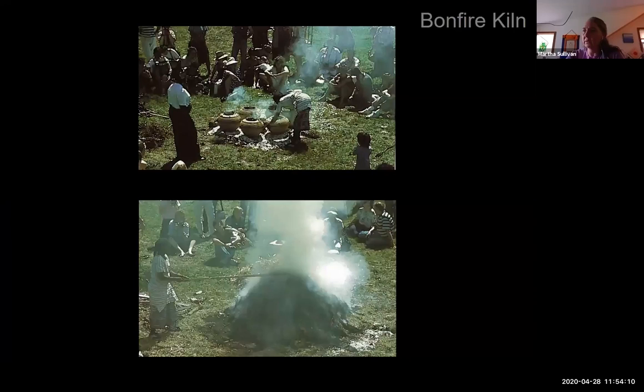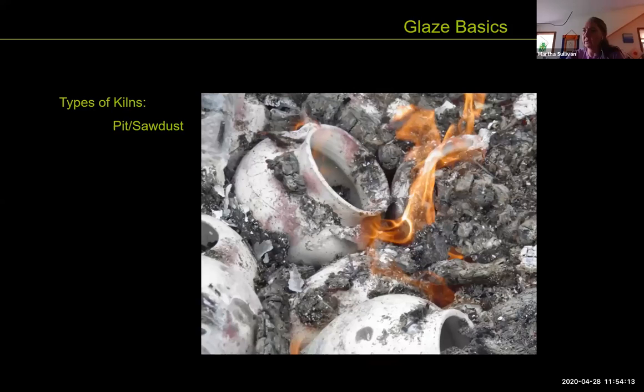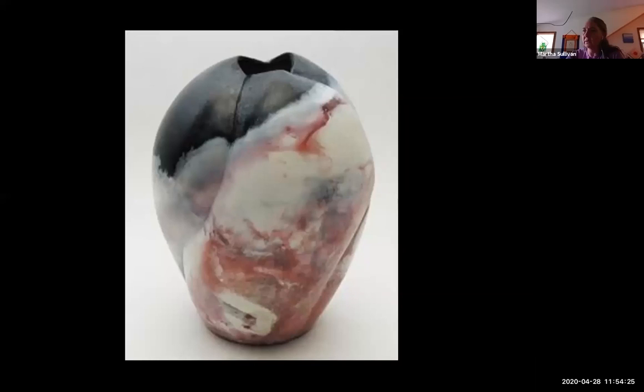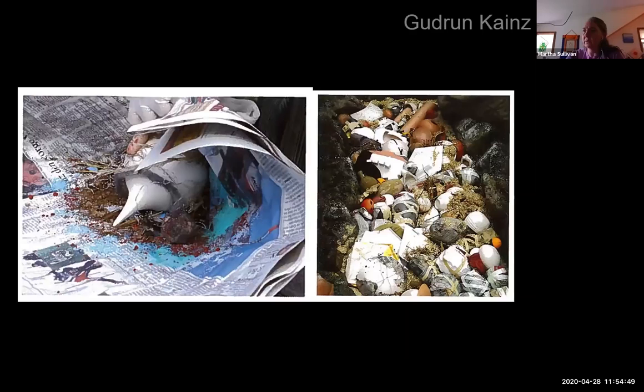So open air firing. From open air, you start to get more heat when you start digging down into the earth. So like pit firing or sawdust firing is a really common way, and it comes up with some really interesting effects. So depending on what kind of materials you put inside of the pit, the colors can be really dramatically different. On this pot where it's black, that means it did not have a lot of oxygen. So it was like a lot of carbon settled on the surface there. And then that red, those things come from other materials you put inside with the pots. And so here you can see somebody like wrapping up one of their pots inside of newspaper, and they put all sorts of stuff in there.